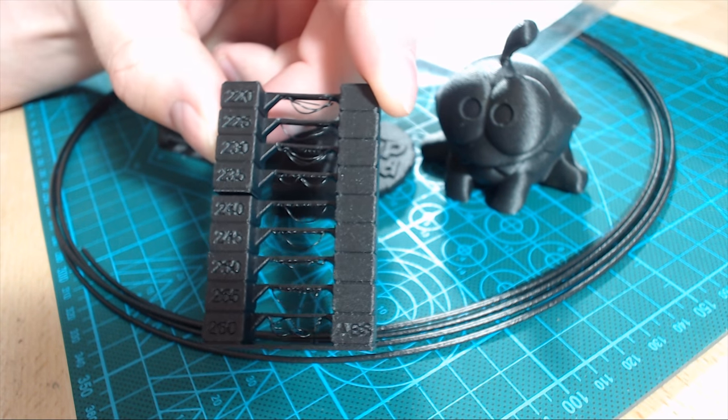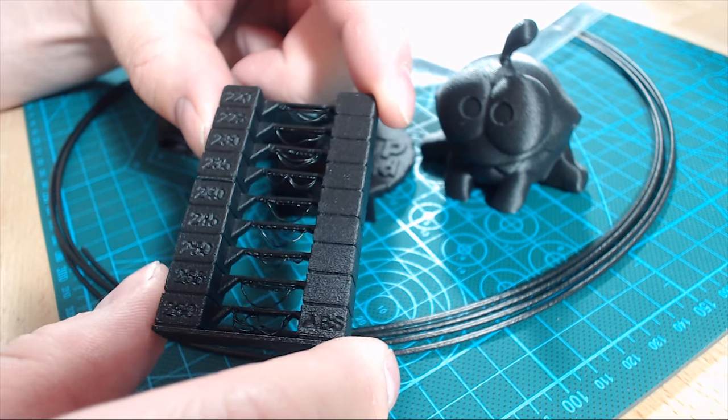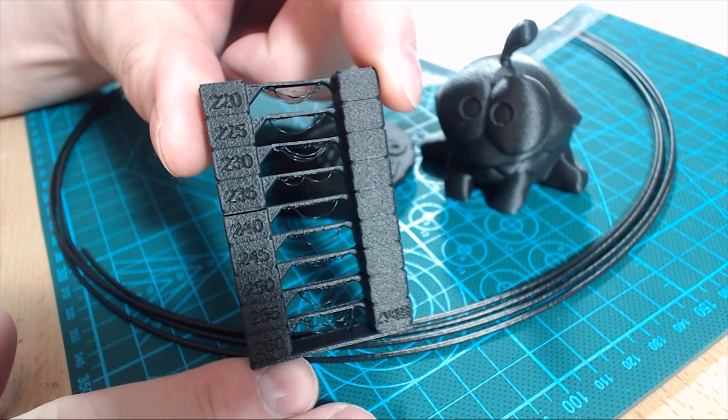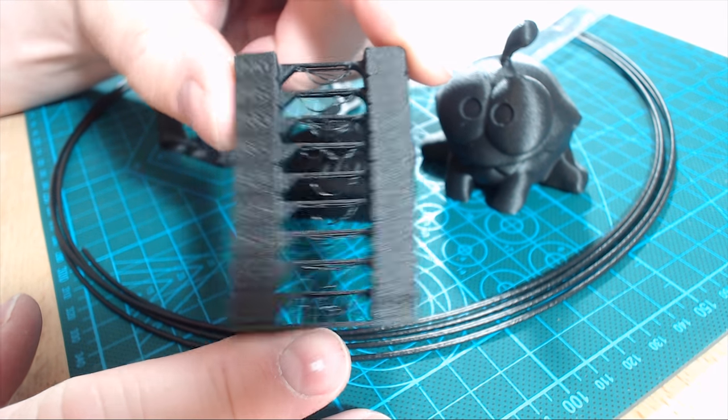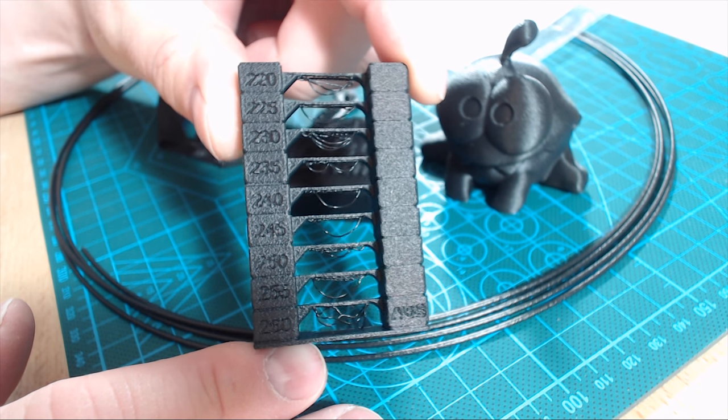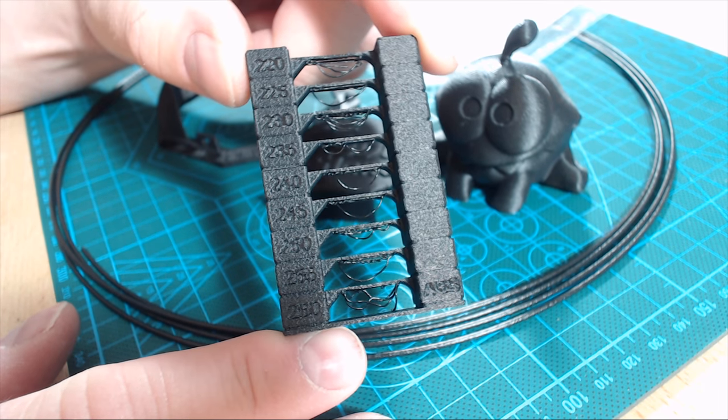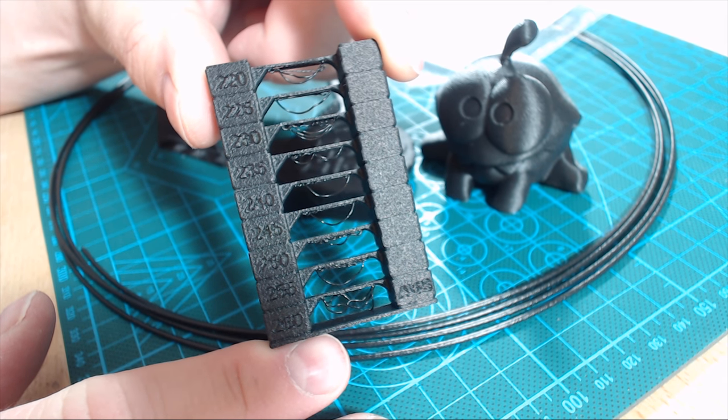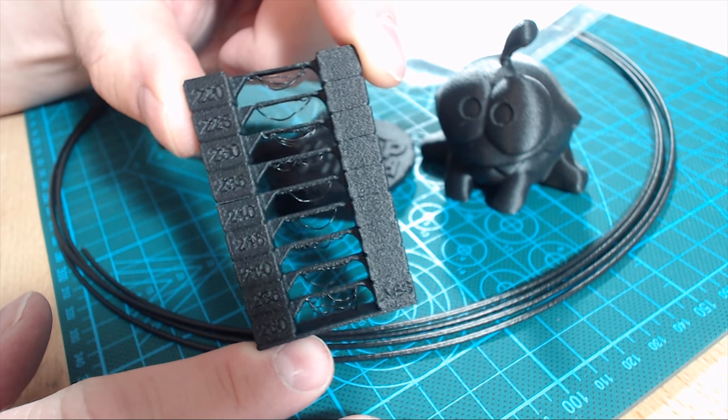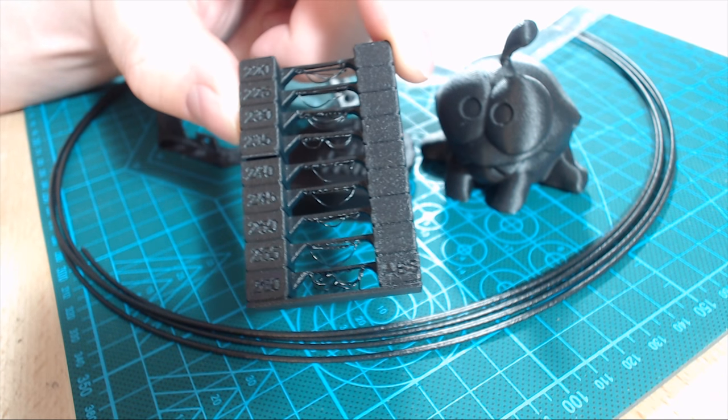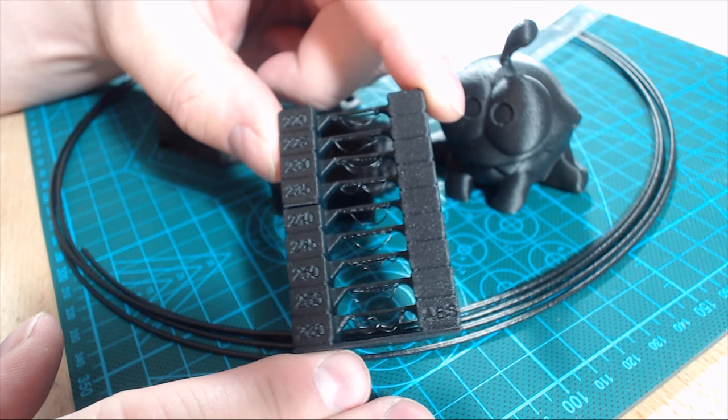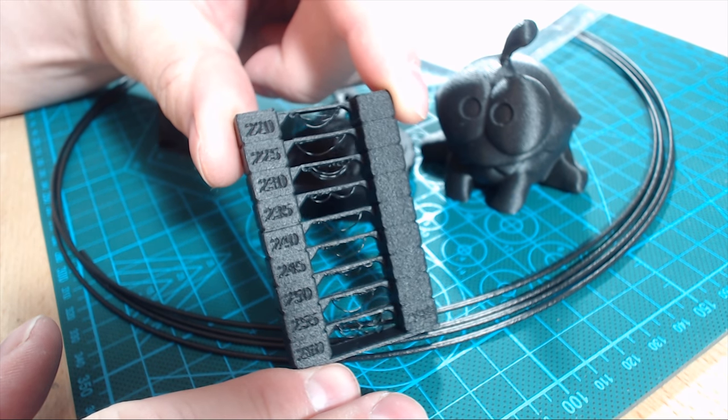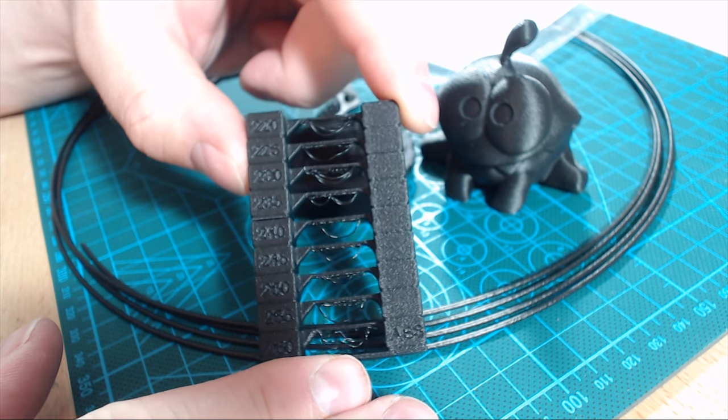To start with, I started with a carbon fiber ABS from PUSH Plastics. I really like the feel of this filament. But the temp tower test on bridging has a bridging test in it. The temperature tower went from 220 degrees at the top to 260 degrees at the bottom. At the bottom the bridging was really bad and around 235 was the best result in the bridging. But as the cooling fan is turned off the bridging is not very good in the other temperatures. But I decided to use 235 degrees on the remaining of the prints.